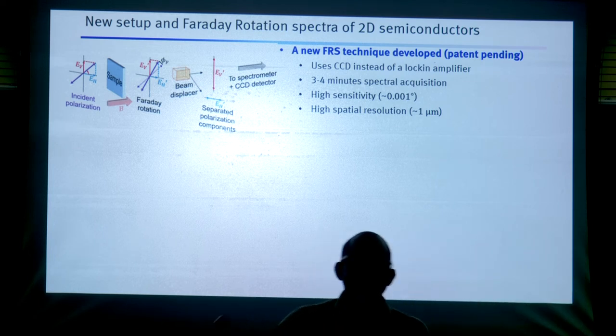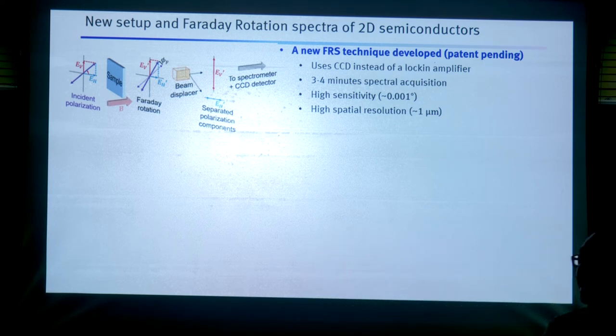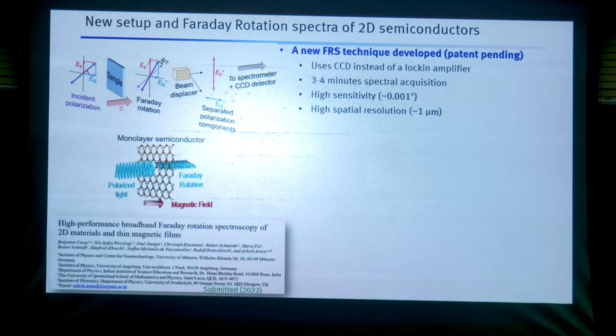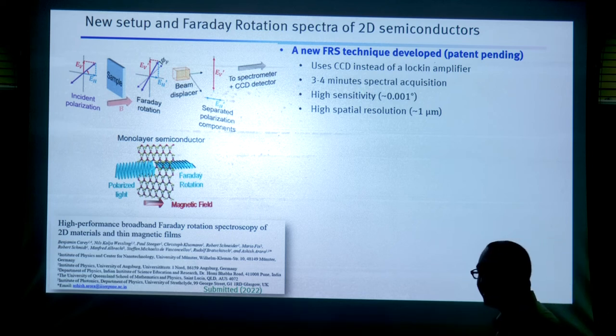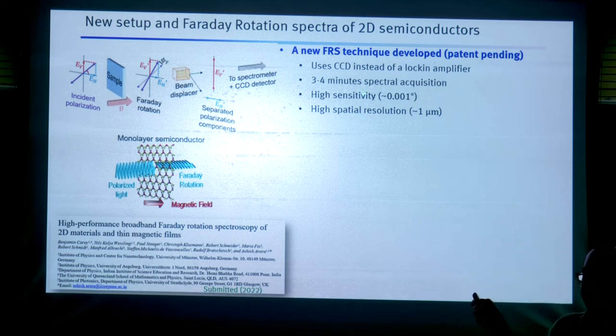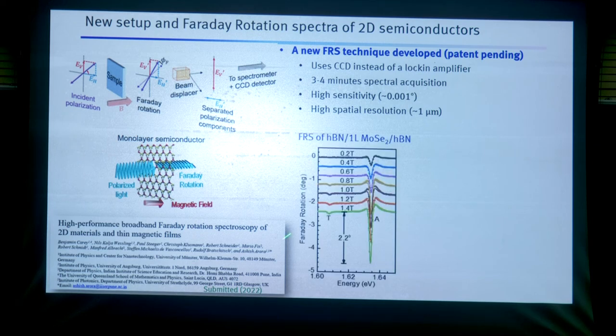And you keep on recording these spectra, and what we find is that within 2 or 3 minutes of measurement time, we are able to get the same sensitivity as that of the previous measurement. So then we are now able to measure things on two-dimensional materials. We have submitted a paper.